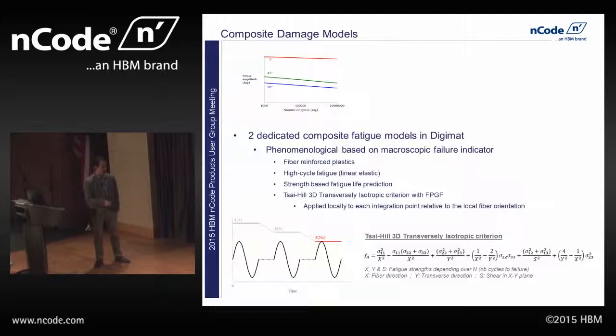And so when we look at that failure indicator, we can see that we've got this X value here, which is going to correspond to the longitudinal strength of the composite. So the strength when the fiber takes most of the load and it's very strong and has this very high stress, low strain at failure. And then we're going to have this Y term here, which takes into account the strength of the material transverse to the direction of the fiber. So when that matrix is taking most of the load and it's not as strong anymore and it's a lot more ductile. And then we have this S term here, which is going to be handling the shear components of the stress. And that's for this scenario where you have this shear loading happening and you have these complex failure mechanisms that are happening as a combination between the fiber and the matrix, like a fiber matrix debonding or a shear failure. So we're going to take this Tsai-Hill 3D transverse isotropic criterion and apply that directly to the individual fibers using our first pseudo-grain failure method.